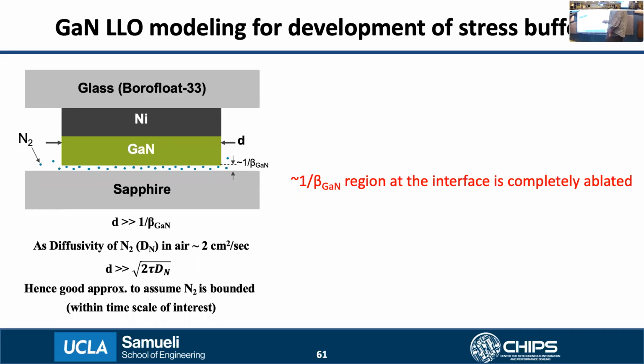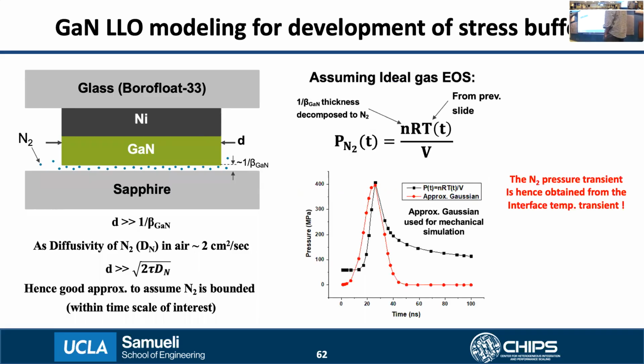For a trapped gas, we can describe it using an equation of state. So this particular gas I have described using an ideal gas equation of state, as you can see here. Using this ideal gas equation, I can extract the pressure of the nitrogen directly from the temperature transient information that was calculated earlier. The number of moles of gas is just the total gas that was decomposed within the beta-GaN region that was ablated. Here you see a plot of the nitrogen pressure as a function of time in nanoseconds. You can see how when the incident light pulse hits, the pressure rises to around 400 megapascals and then starts falling off as the heat is conducted away, which we have approximated by a Gaussian pressure pulse for use in our full ANSYS simulations.